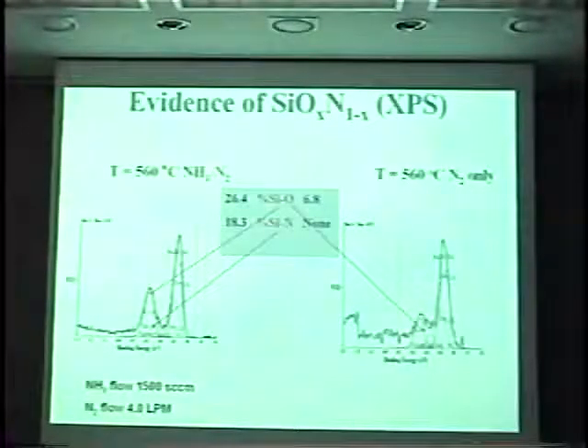And if we go look at XPS to look at the bonding structure, you see that if we expose this surface to ammonia, with our cleaning process, we get evidence of both silicon-oxygen and silicon-nitrogen bonds. We use only inert nitrogen. We have no evidence of the silicon-nitrogen bond, although there's a little bit of residual SiO, either coming from the reactor itself or from just beneath the surface.